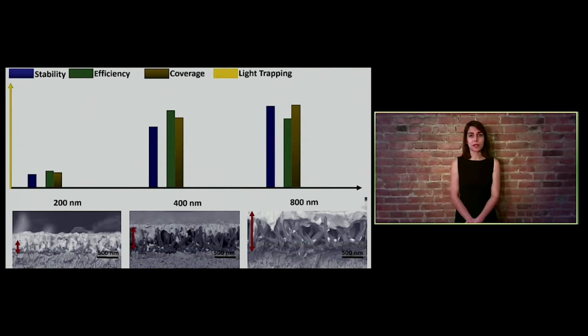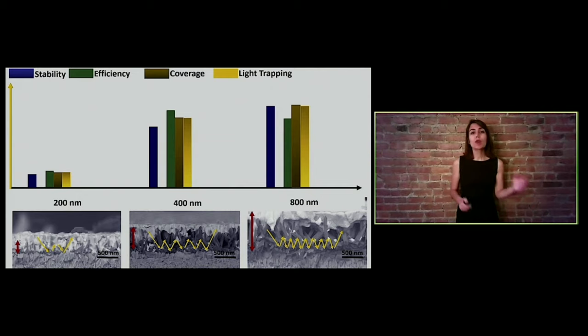There is one more aspect to this. When light enters each one of these structures, it is going to have a limited number of interactions before it finally manages to escape. The number of interactions that light has with solar cells based on longer nanorods tends to be higher. This is because there are more surfaces to bounce off of. This essentially means that we are trapping the light and then recycling it over and over again, and as a result, creating more charges. But this by itself creates a big question.